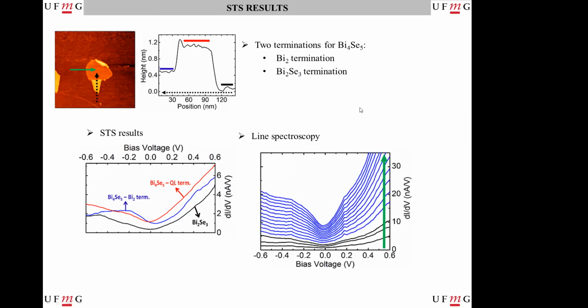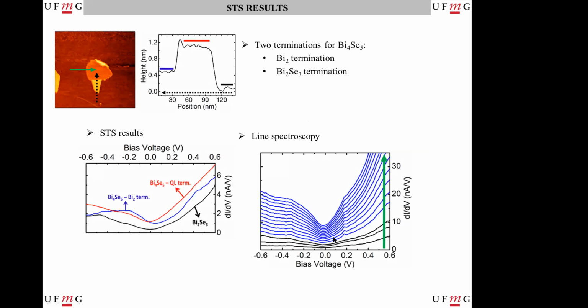Another thing that we could do using STS on our sample is that we can try to make a line spectroscopy here. What that means is you can do a spectroscopy on each point here, approaching the nanograin, so you can see the changes in the density of states of the sample when we go from bismuth two selenium three to bismuth four selenium five. And we can see here that the new characteristics of the sample start to appear, and the sample becomes more metallic when we enter the bismuth four selenium five. So this was an example of using the STS spectroscopy to differentiate between two kinds of structures in a material